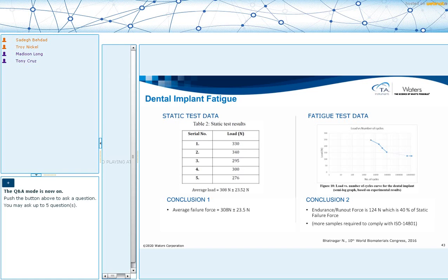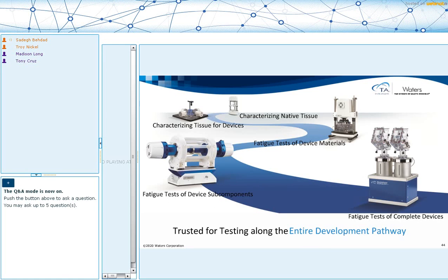So remember, in the initial graph that we discussed, the Basquin line looks linear, but it's a log-log plot. So it's actually an exponential improvement in fatigue life when you reduce the stress. And so they found out that 40% of the maximum static failure force is where you can get your endurance limit and sort of infinite fatigue life. And that's consistent with other literature values. A lot of times, at least for pure materials, you'll see that your endurance limit is somewhere between 30 to 40 to 50% of your maximum static strength, and this is right in the middle of that.